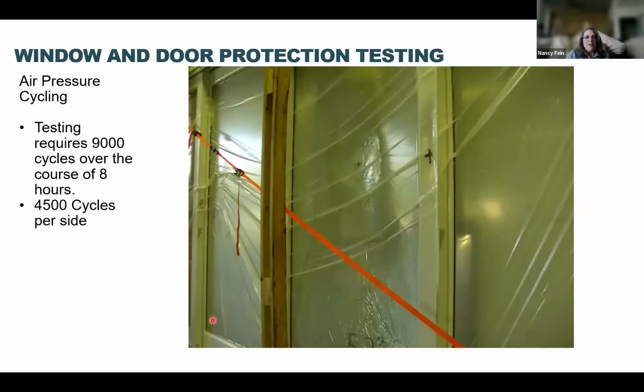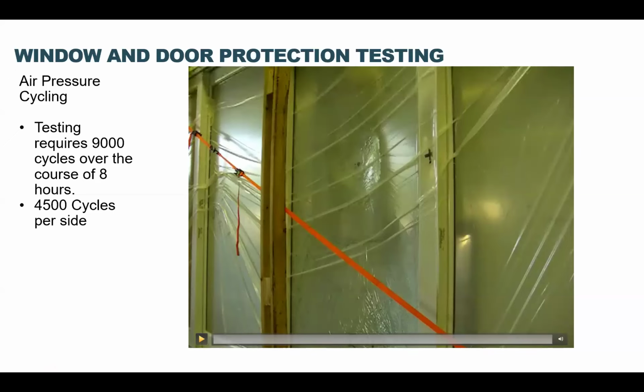And that's pretty much reiterating what Chris just said, that the testing requires 9,000 cycles over the course of 8 hours and 4,500 cycles per side. So obviously you're testing it from both sides. It's pretty self-explanatory. Going back to what Chris said a moment ago about the height, that is why you have greater issues in high-rise buildings than you do in single-story or mid-rise buildings, because as you go higher, the wind speed changes and increases exponentially. Right, and I don't believe the same type of debris is set aloft by high winds. All the larger stuff is generally below 30 feet.